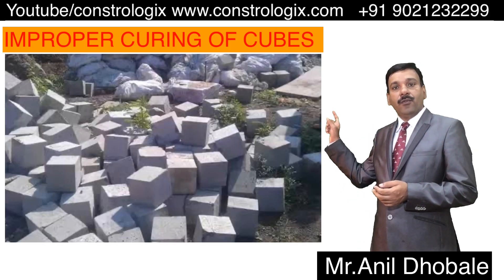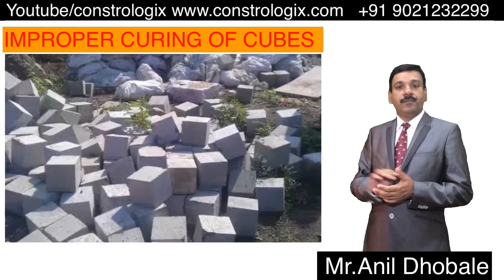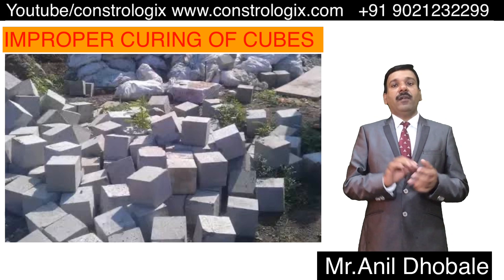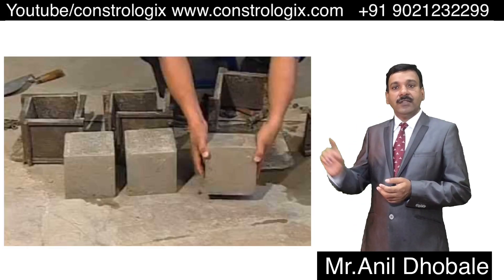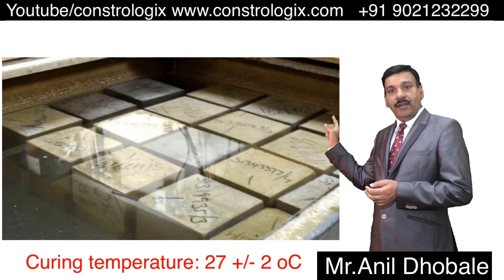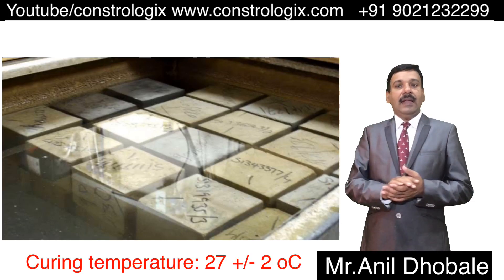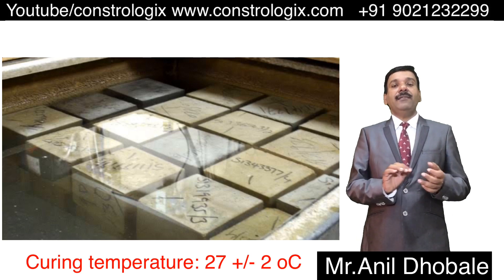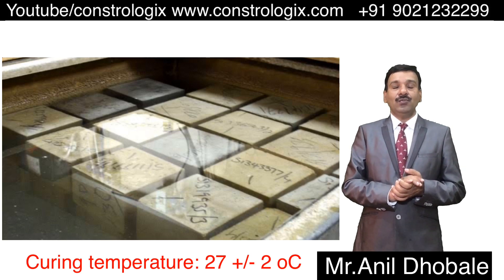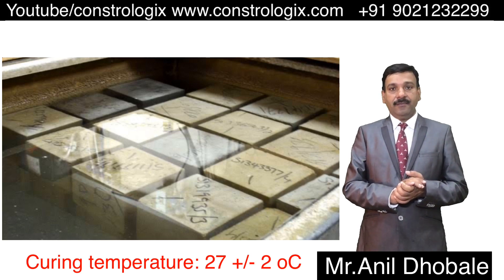Improper curing of cubes. After 24 hours of casting, cubes shall be placed in a curing tank at a temperature of 27 plus or minus 2 degrees centigrade.